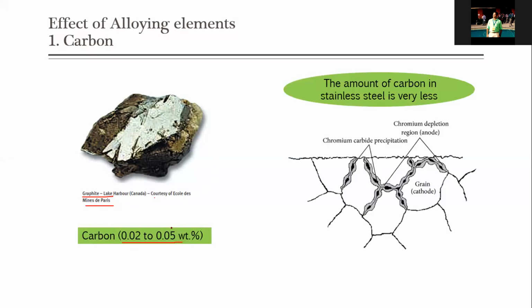Carbon is not essential in stainless steel because of the sensitization problem. If you have more carbon in your alloy, it extracts the chromium content to form chromium carbide precipitates near the grain boundaries. Hence, carbon is largely eliminated from stainless steels. If you have this sensitization problem, you will have a decrease in corrosion resistance. Hence carbon is avoided, and the amount of carbon will be very low in stainless steels.